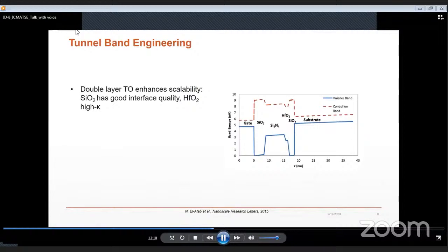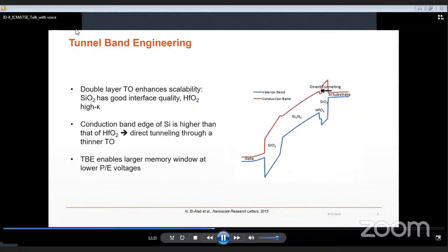However, using the double layer, when the applied voltage across the silicon dioxide layer is high enough, the conduction band edge of the silicon channel becomes higher than the conduction band edge of the hafnium dioxide, leading to direct tunneling across a thinner silicon dioxide layer than in the case of a single tunnel oxide, leading to a larger memory window. In addition, with the retention characteristic, studies showed that the double layer has a retention time which is slightly smaller than that of a single silicon dioxide layer. This is due to the fact that there is no larger barrier between silicon nitride and hafnium dioxide for the trapped electrons due to the higher electron affinity of hafnium dioxide. Nevertheless, we have shown that the 10 years data retention is not compromised.